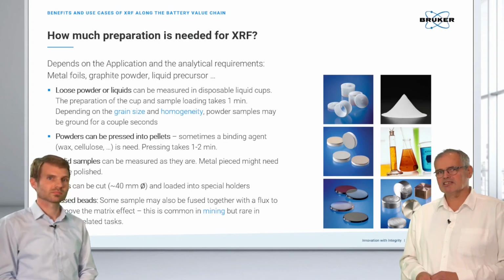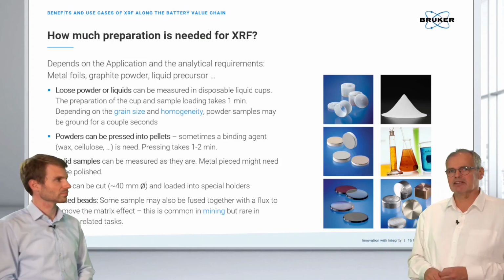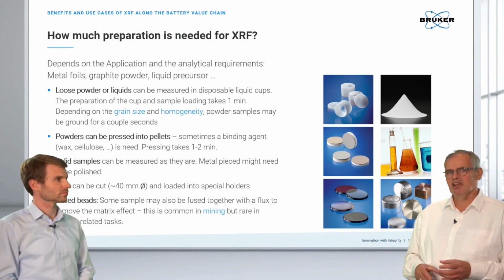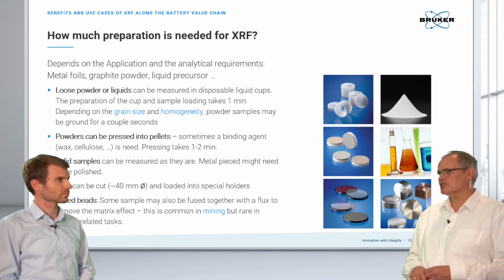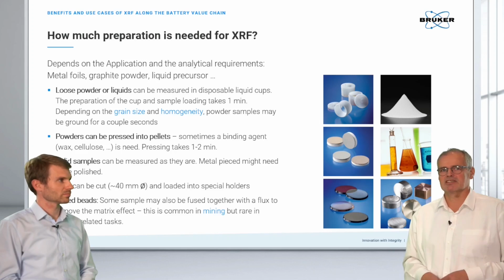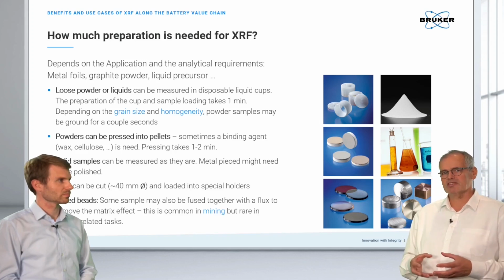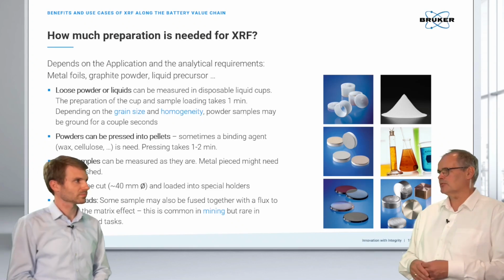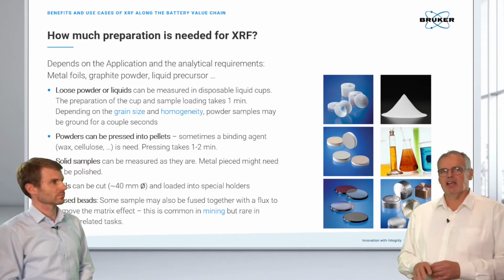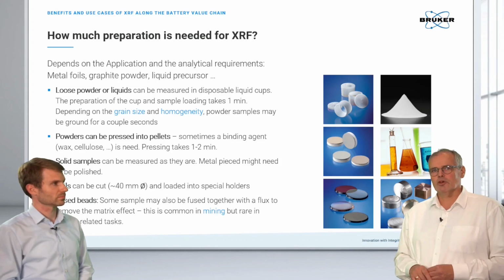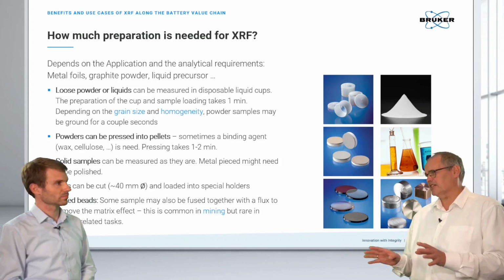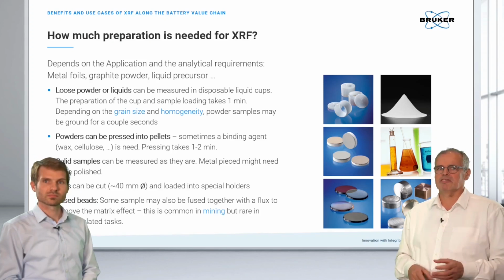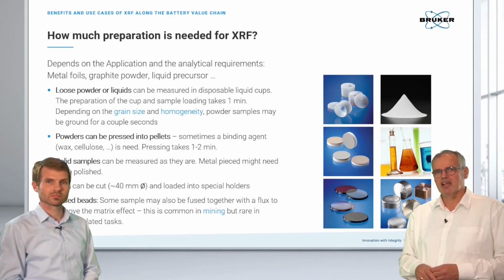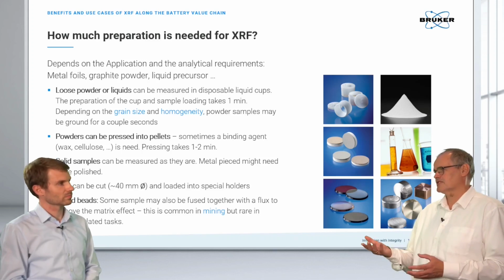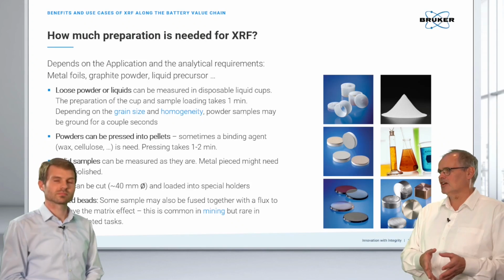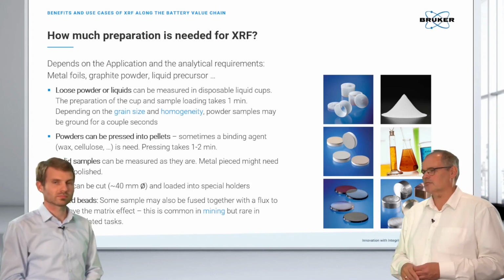And last but not least, this is not a topic for today, but for some reference samples, for very high accuracy and very good precision, we can melt the sample with some borate salt and transform the sample into a stable glass bead. So then we have a very homogeneous result. The thing is, we are not working with just 100 milligrams. This can be done as well, but typically we are working with a sample amount of 5 to 10 grams, which also helps to increase the representativity of our specimen analyzed to the big batch we see in the production.